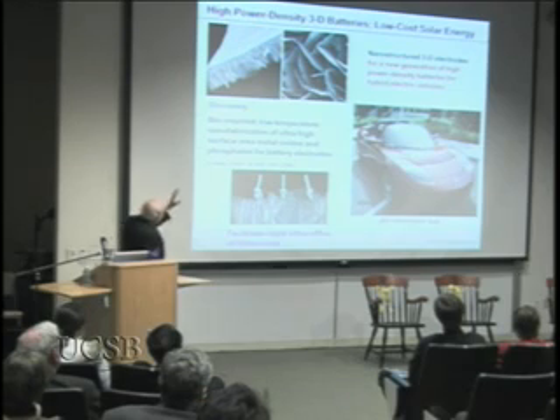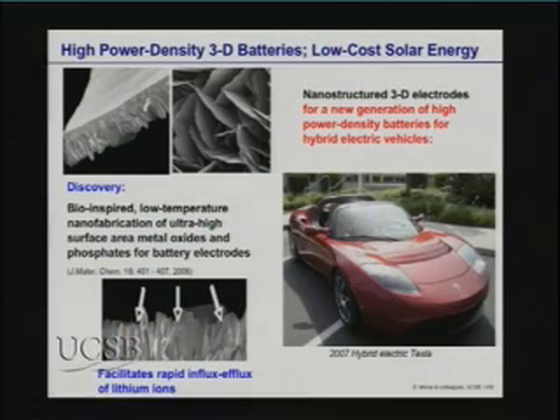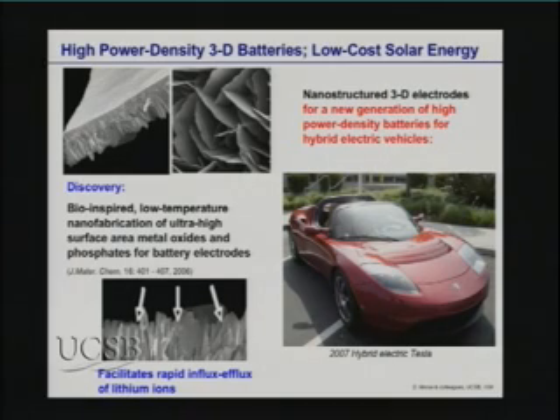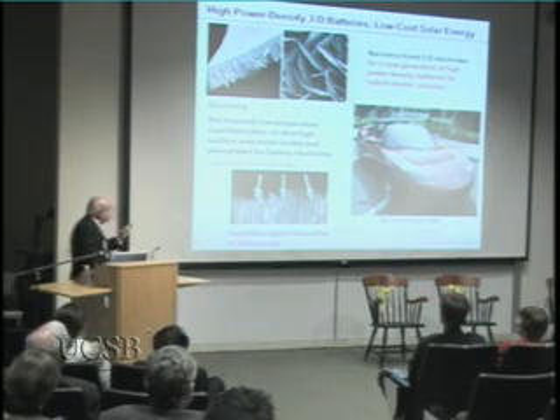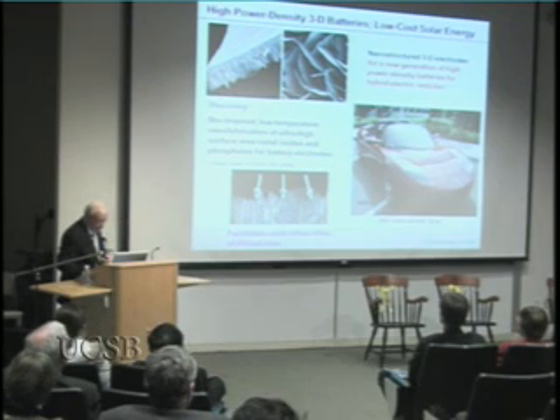For example, because of the very high surface area of materials, metal oxides and phosphates that we can make this way that are potentially useful as lithium-ion battery electrodes, the lithium ion can gain very rapid access into the plates of the semiconductor and out again. That high flux rate of the lithium ion suggests to commercial partners here in Southern California that they would be useful for three-dimensional high-power density batteries such as needed for the next generation of hybrid electric vehicles. Similarly, the high surface area also proves useful for low-cost, higher efficiency solar energy. And so we're pursuing that application as well.